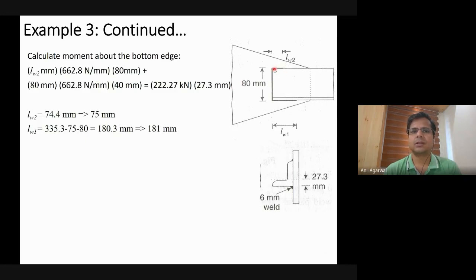So what we will do is calculate the moment. The idea of distributing this weld is that the moment applied because of the external load, that is the design strength of this angle, and the moment because of this weld should cancel each other out. So we will take LW2. If I take moment about this line, then this weld will not contribute towards the moment, because this weld is exactly at the same location as the point we are considering the moment about. This weld will contribute and this weld will contribute. This is an 80 millimeter weld and its centroid is 40 millimeter away. This is LW2 long weld and its centroid is 80 millimeter away. And there is a force acting 27.3 millimeters away. So I know all the ingredients. I just need to put them in the equation.